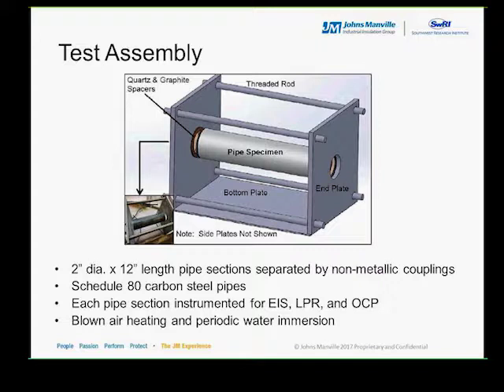Two test setups were used depending on the upper temperature limit. The test assembly shown is commonly used for high temperature environments in the order of 700 to 800 degrees Fahrenheit. The lower temperature setup, up to 500 F, uses inline pipe spools for practical purposes. For all the cases, the CUI test assembly involves the use of coated or uncoated pipe, a thermal insulation, and a metal sheeting.